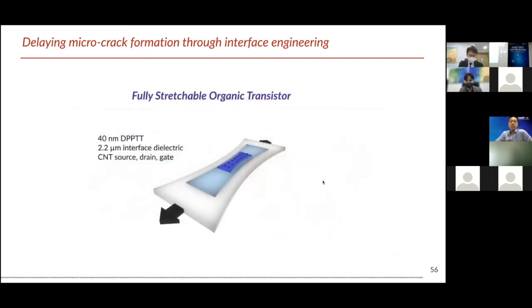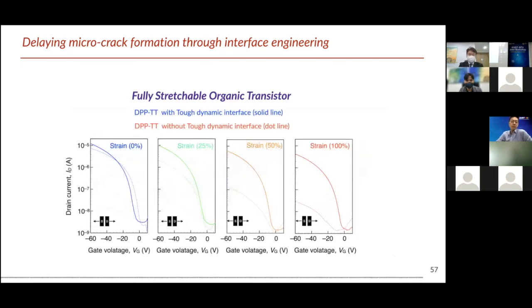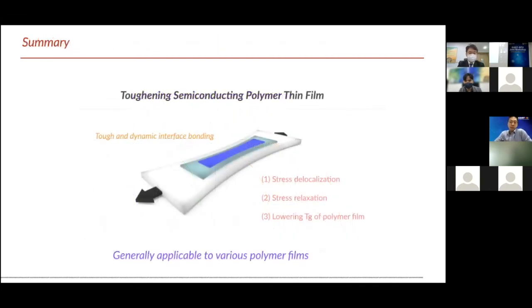And based on this material, we were able to fabricate a fully stretchable organic transistor by using our interface as a dielectric. Based on this approach, you can see that up to 100%, we can see a very nice transfer curve. But without the tough interface, you can see a significant drop of the current level because of the crack formation. This means that our approach is truly useful to fabricate stretchable organic devices. And actually our approach is quite general, so it can be applied to various polymer films, even PEDOT:PSS and also gold layers. So this may be a new paradigm shift in the engineering of stretchable electronics.